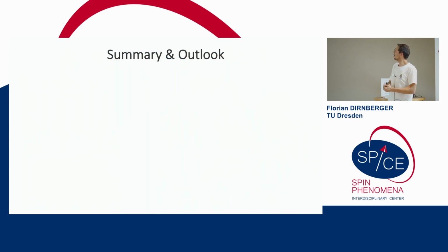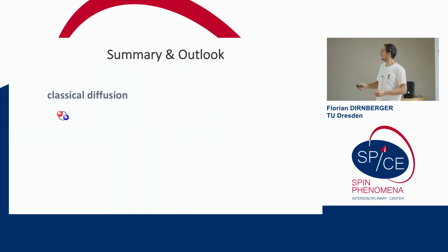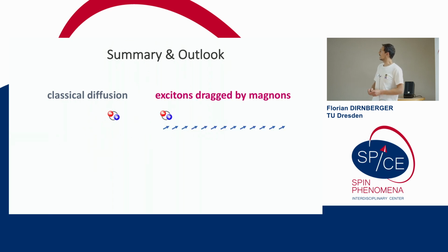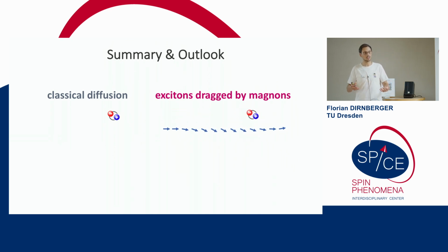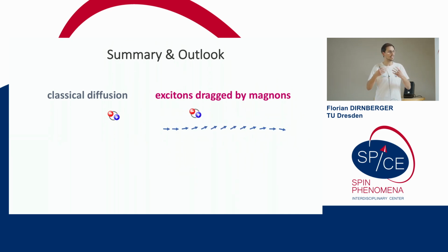Okay, so with chromium sulfide bromide, we were able to look at the transport of excitons in a magnetic material. We started out with an expectation of classical diffusion, where the excitons would be anisotropic and slow. This is what we see in most semiconductors. It seems that in this magnetic semiconductor, things can be a little bit different. Every experimental signature that we found in this study seems to indicate that instead the excitons are dragged by the magnons, because they move very fast, they move isotropically, and they have this maximum at the Néel temperature. These are all things that we wouldn't really expect from diffusion, but their coupling to magnons would allow us to rationalize a lot of these things.